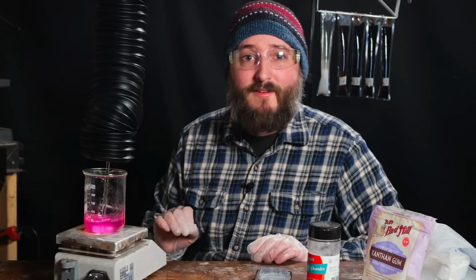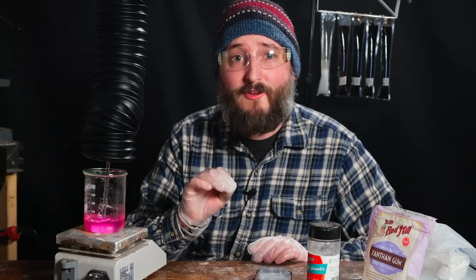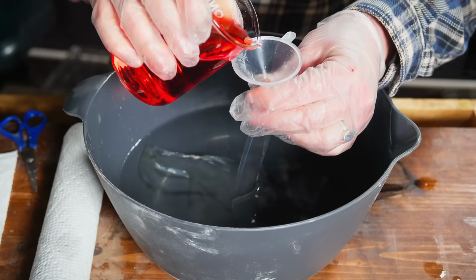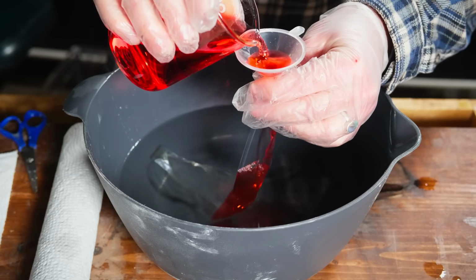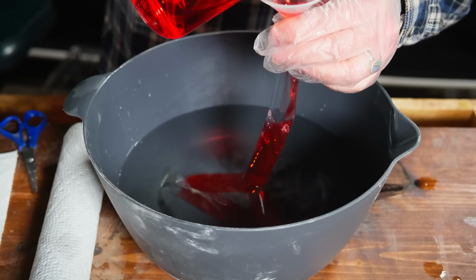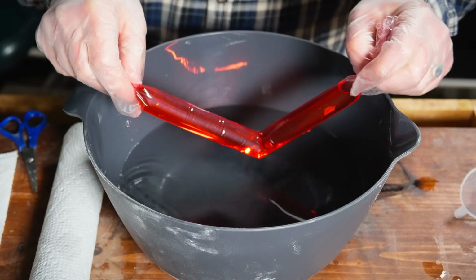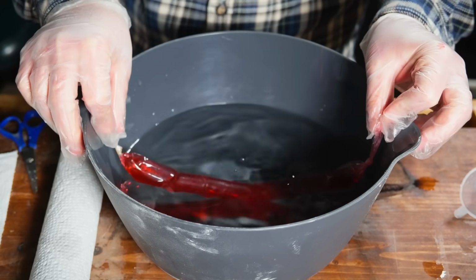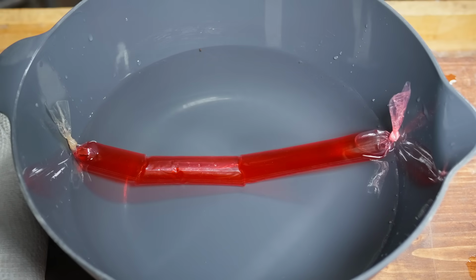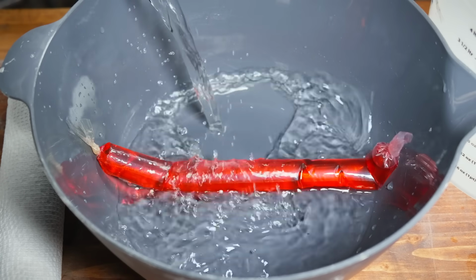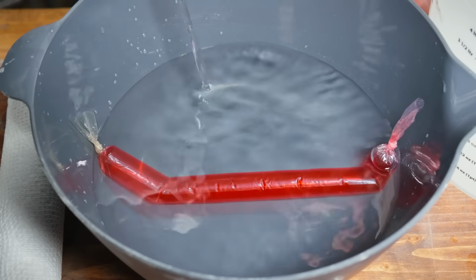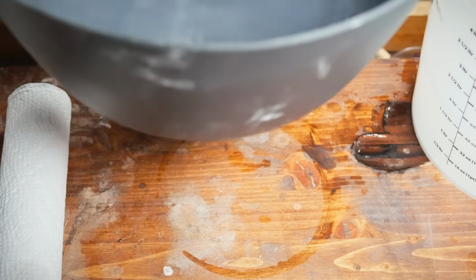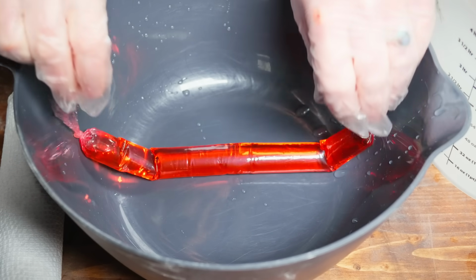You can do the same thing to separate chemicals in the lab by using a semi-permeable membrane, often a tube made out of cellophane. You fill this tube with the products of your chemical reaction, like a weird sausage, and put it into a bowl of deionized water. The small molecules can seep out into the water, but the larger polymer molecules stay trapped in the tube. After changing out the water several times over the course of a few days, all the salts get washed out, and the contents of the tube can be dried to collect the purified polymer.